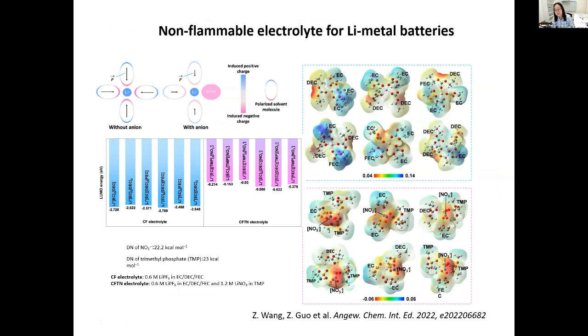The first example I would like to share with you is a liquid non-flammable electrolyte we developed for the lithium metal battery. You probably know that to achieve non-flammability, we often need to add a fire retardant. But lithium metal is not stable in the fire retardant. So to make it stable, we added a second lithium salt. This is lithium nitrate. This lithium nitrate has a similar donor number to the fire retardant, in this case TMP. So these two components have similar donor numbers. Therefore, the nitrate can readily be involved in the solvation structure of the lithium ion.